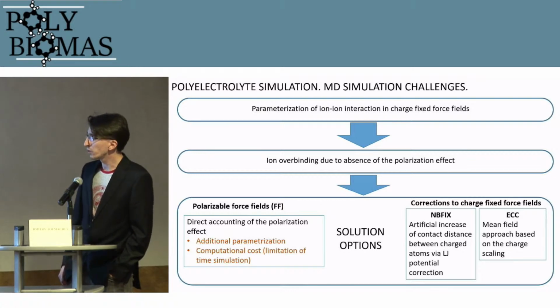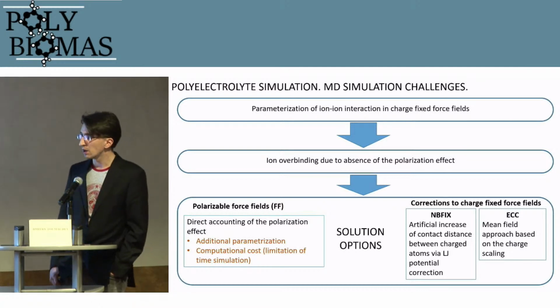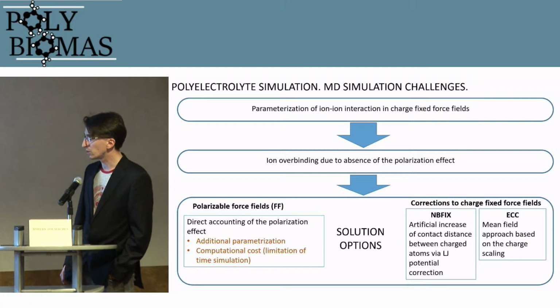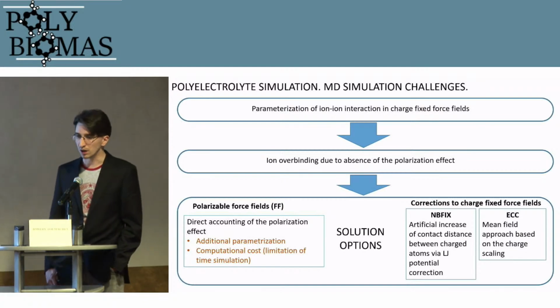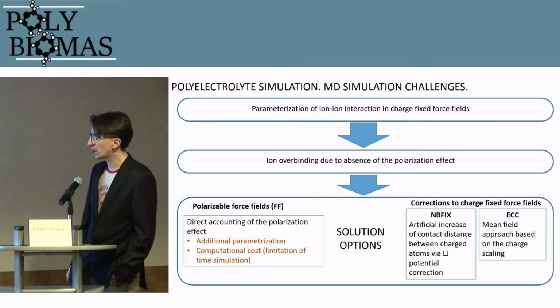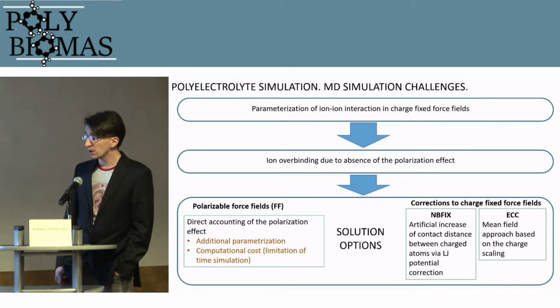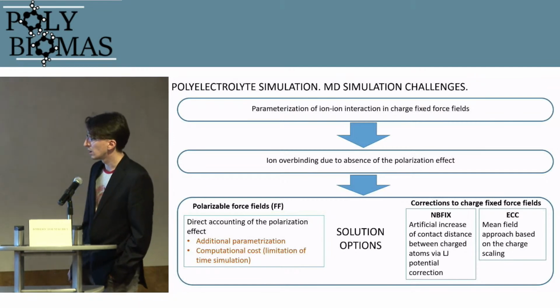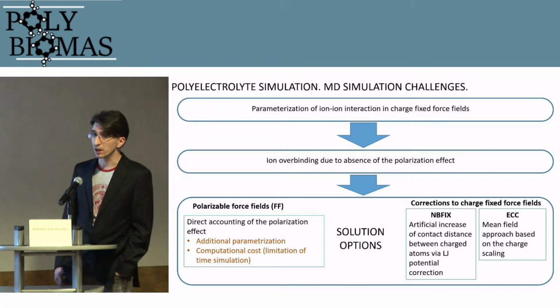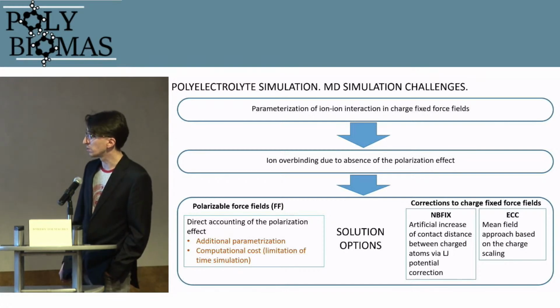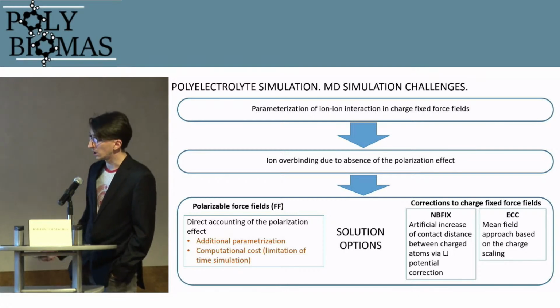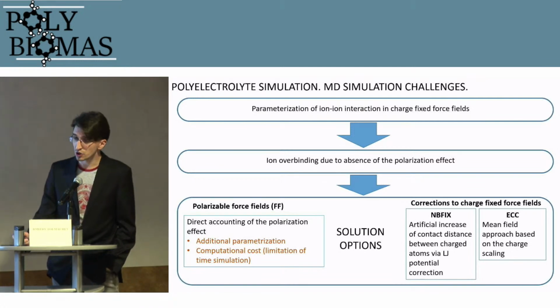So it's preferable in some cases to use corrections to charge-fixed force fields, such as NB-fix, which is based on an artificial increase of contact distance between charged atoms. Or electronic continuum corrections, which was described yesterday by Hector, and it's based on a mean field approach and charge scaling.